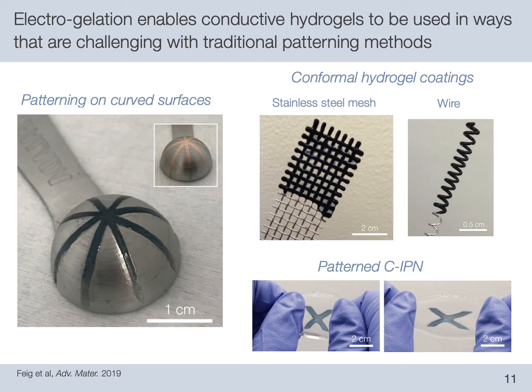The method is also compatible with making conductive interpenetrating network gels, as the patterns can be backfilled with secondary network monomers and polymerized to create fully stretchable embedded conductive patterns.